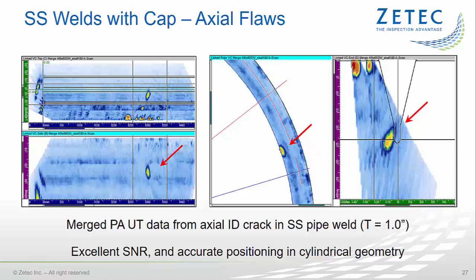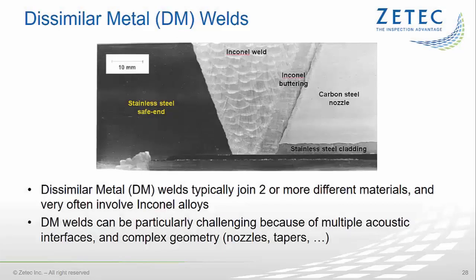The different views, including the onboard polar view, show that the actual ID crack is accurately positioned in the heat-affected zone on the ID of the pipe. The crack was detected with various skew angles, and a high signal-to-noise ratio can be observed. This inspection technique was demonstrated to be quite effective for the detection of essentially axial cracks. Let's now move on to a different type of weld.